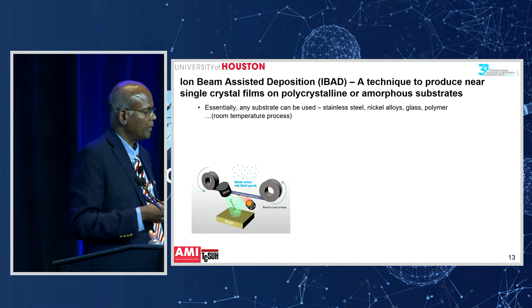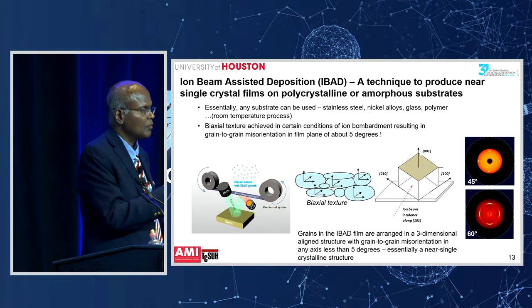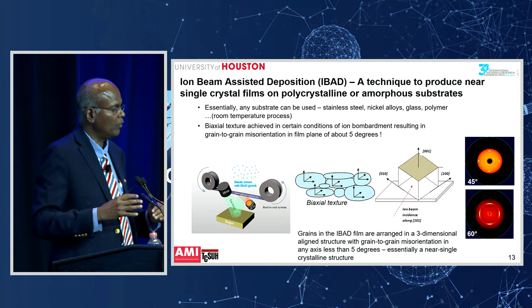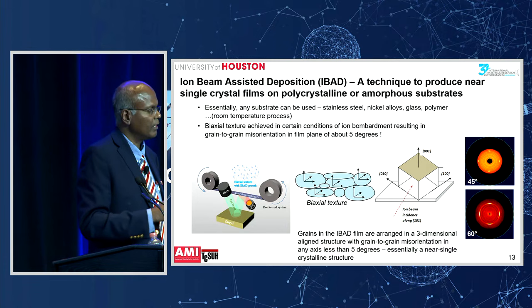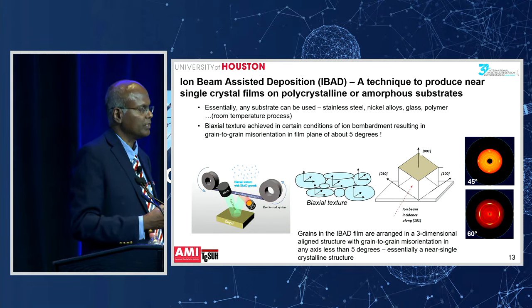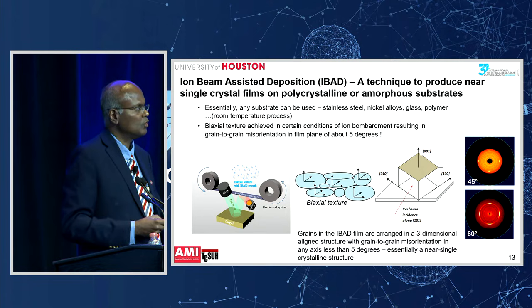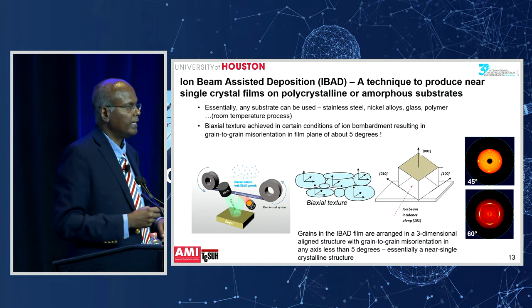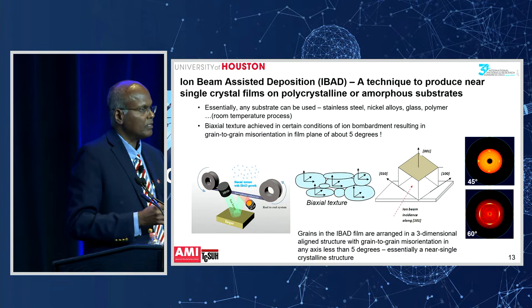And while you're depositing this, you're also bombarding the film with low-energy argon ions along a certain direction. This is the ion channeling direction, which for a cubic material like magnesium oxide is the 101 direction. If you do it along the 45 degree angle, what you get is biaxial texture. You can see in the cartoon that the grains are aligned with respect to each other within a few degrees. You can see that in the X-ray pole figure on the right-hand side: with the ion beam along 45 degrees, you get a very sharp texture where the grains are aligned within, say, 5 degrees.